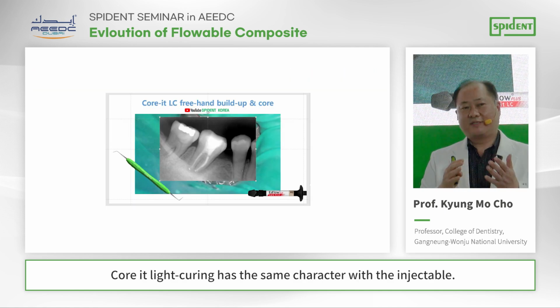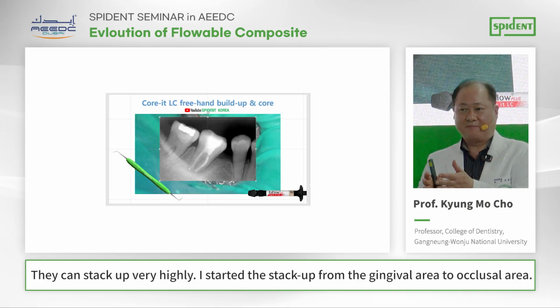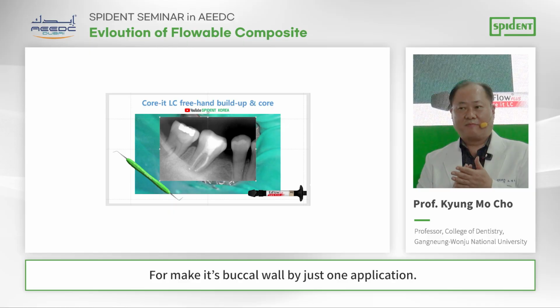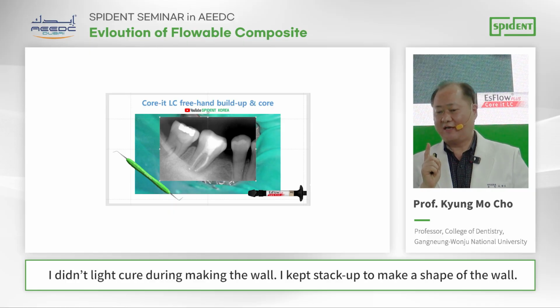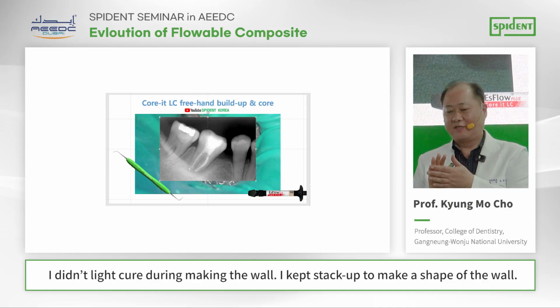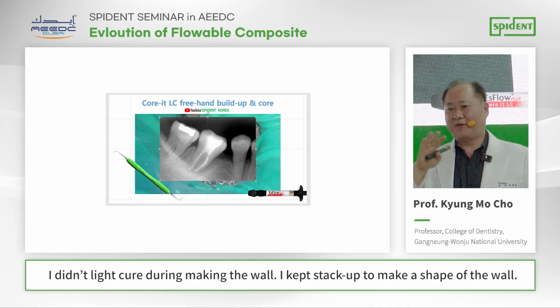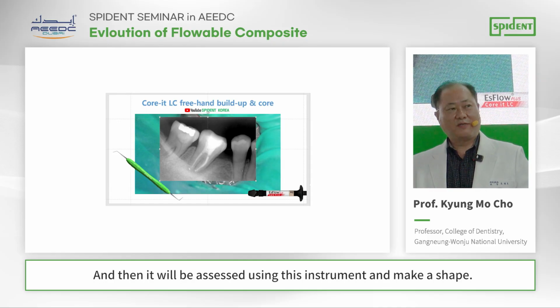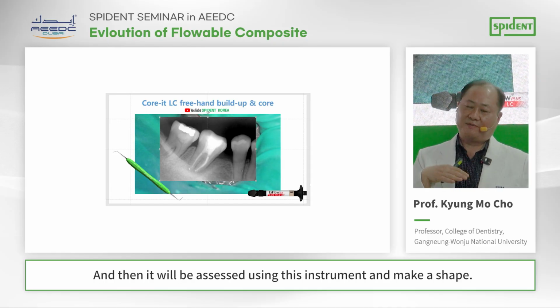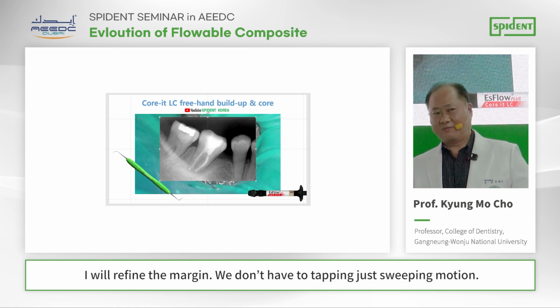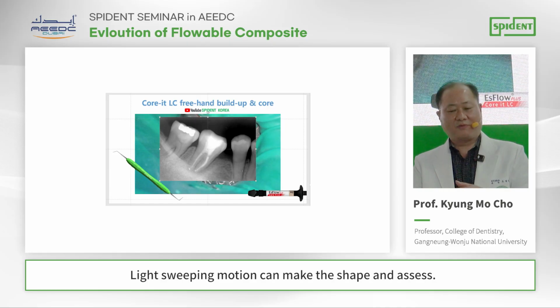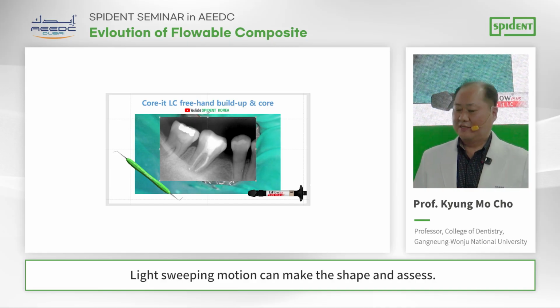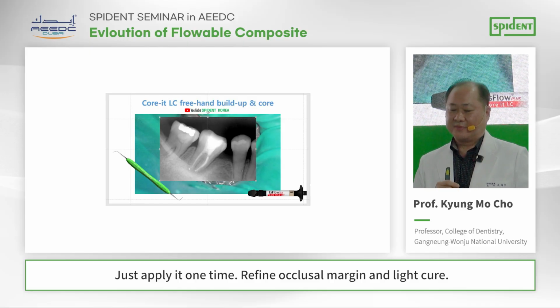Core light curing has the same character as the injectable. It can stack up very highly. I start the stack up from the gingival area to the occlusal area, making the buccal wall by just one application. I didn't light cure while making the wall. Keep stacking up to make the shape of the wall, and then recess it using this instrument to make a shape and a really fine margin. You don't have to tap, just a light sweeping motion can make the shape, and then it will recess. Just apply it one time, refine the occlusal margin and light cure.